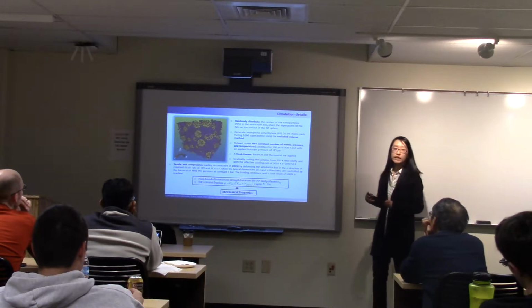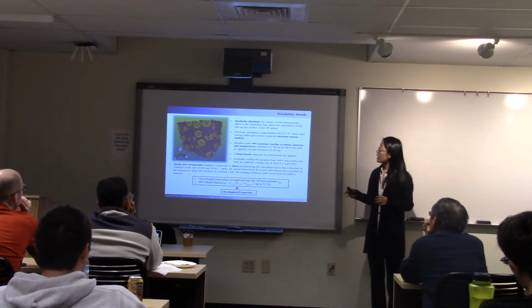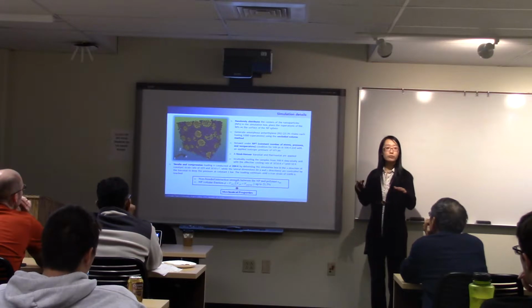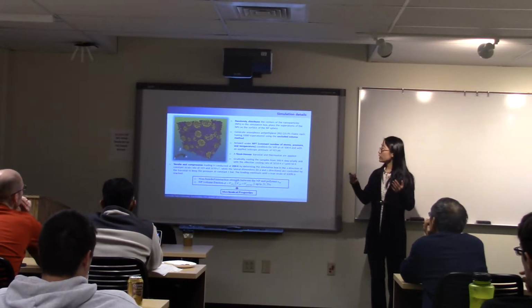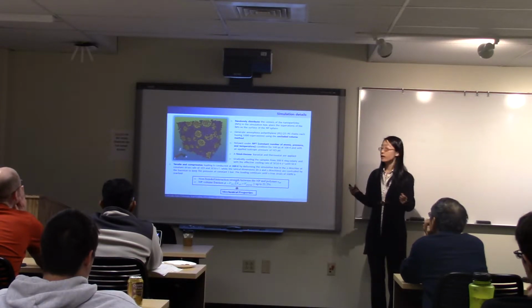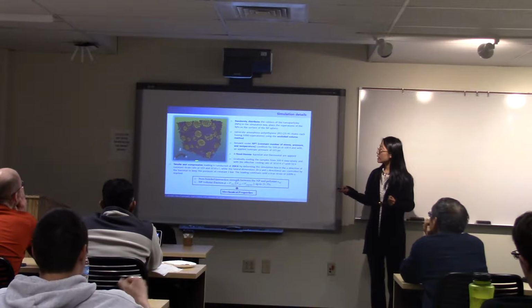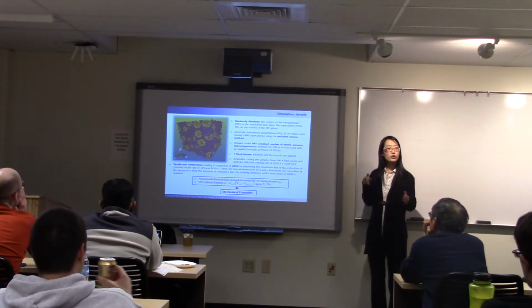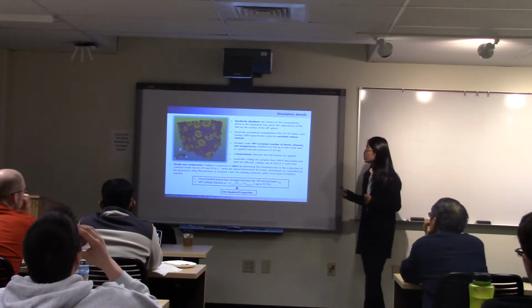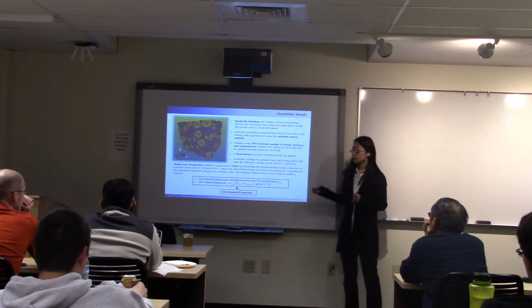This gives some simulation details on how we construct the system and equilibrate it, as well as gradually cool it down to lower temperature. And finally, we apply some uniaxial loading, both the tensile loading and compressive loading at 200 Kelvin until a true strain of 100% is reached.